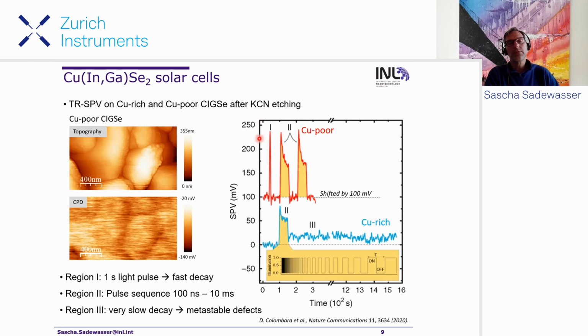Of course, this way of just switching light on and off does not allow us to learn anything about the dynamic processes. Therefore, we use these pulse sequences that were already introduced before. So we start with very fast pulses and then go slower and slower. And we run this pulse sequence here. And what happens then, if we just observe this in real time, we see initially a strong increase, and then we see this drop here. And of course, this is as a function as we are keeping these pulses on. In these experiments, we used pulses between 100 nanoseconds and 10 milliseconds period.